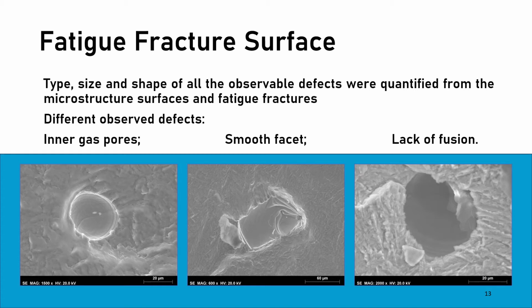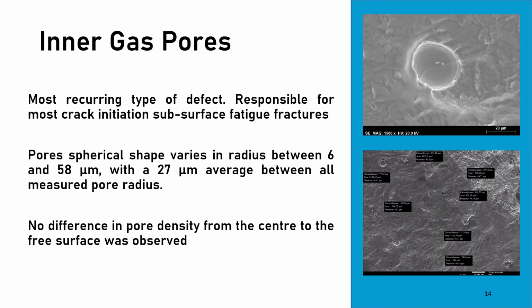Three types of defects were identified through the fracture surfaces and microstructural samples: the inner gas pores, the smooth facets, and lack of fusion. Now, a deeper analysis of the inner gas pores was conducted since it was the most recurring type of defect and was the most responsible for crack initiation at the subsurface.